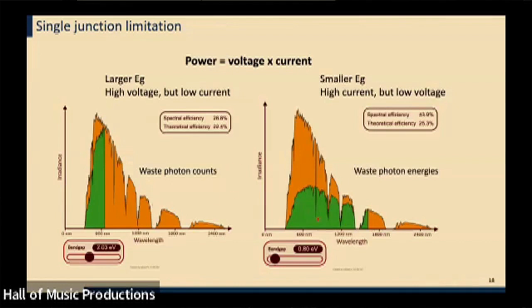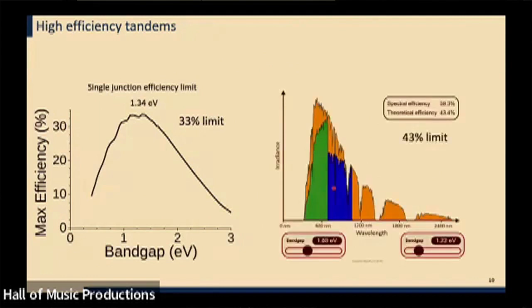Another way to say that is that all these juicy energetic photons in the visible are going to very quickly have much of their energy lost to thermalization inside the semiconductor. And so this leads to a compromise if you make a device using a single junction approach. And it leads to this upper bound of a little above 30% for the solar power conversion efficiency.